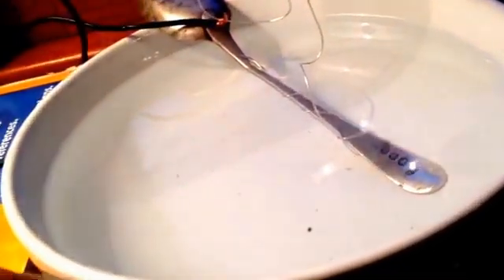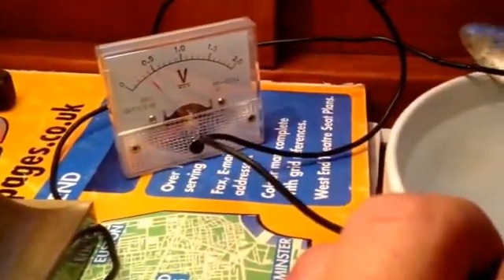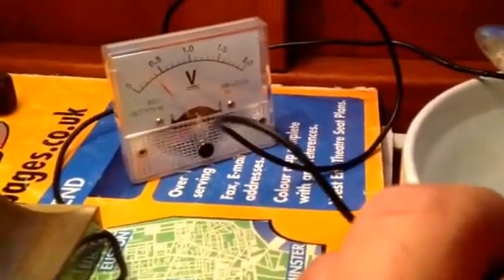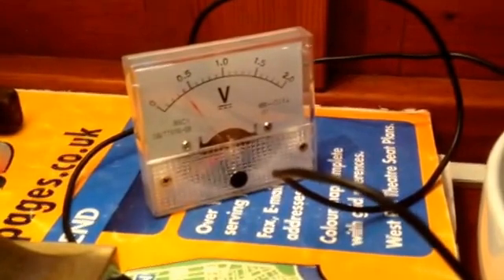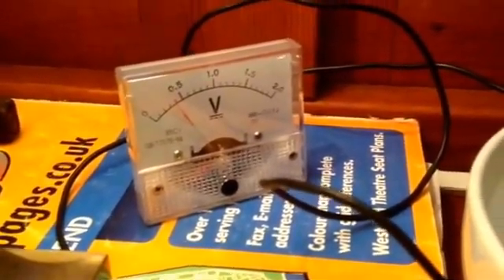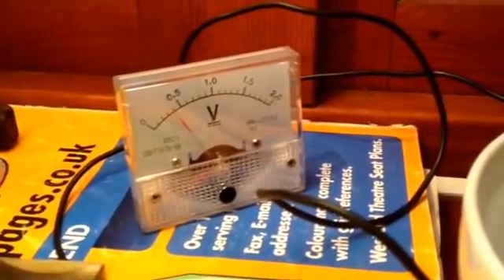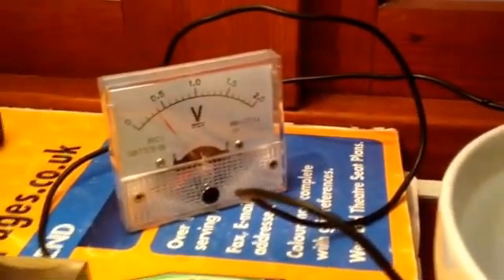Let's put this great big nut on — in that goes — and there we go, right up to close to 0.4 volts. As I say, these voltages should be a bit different but this is a very poor multimeter. That's a perfect galvanized never-used nut, so that's zinc all the way through.